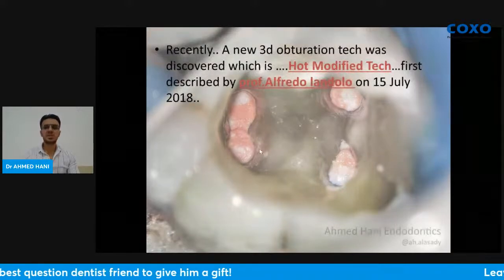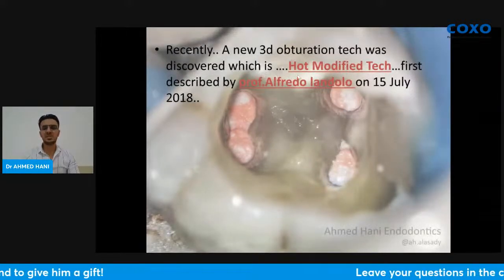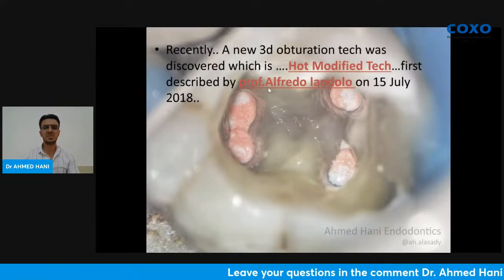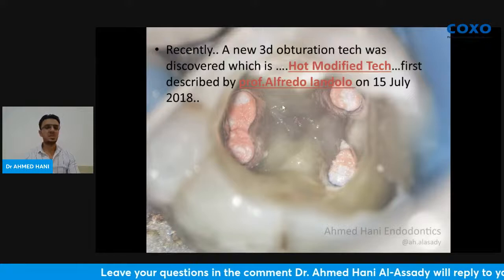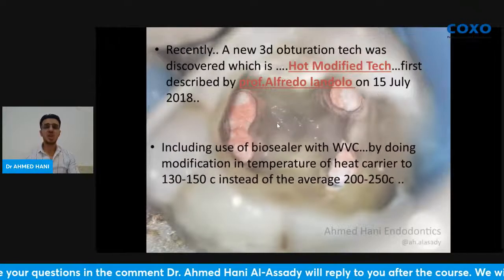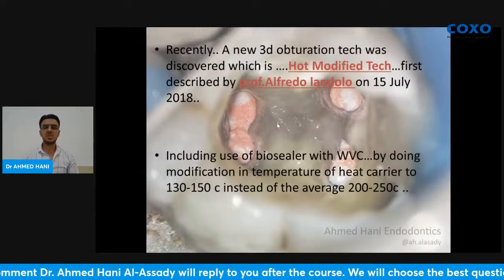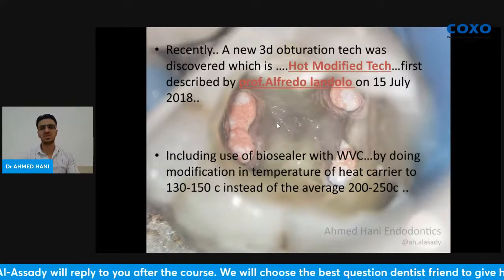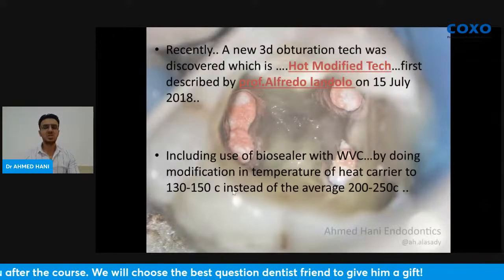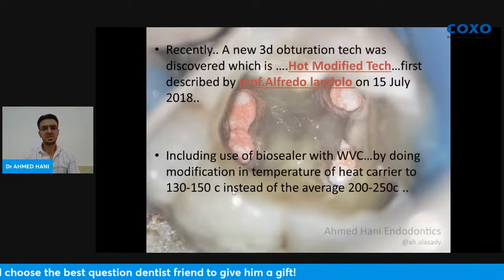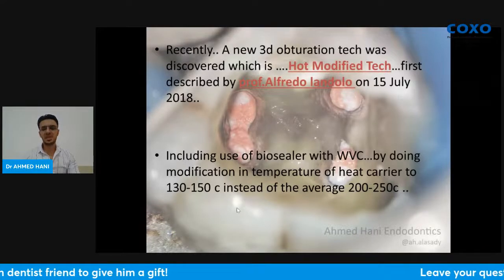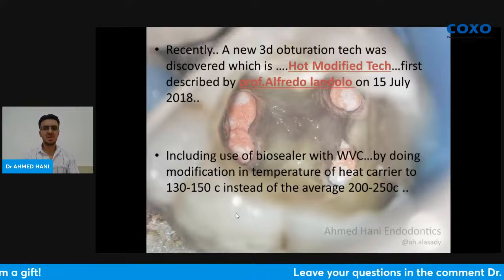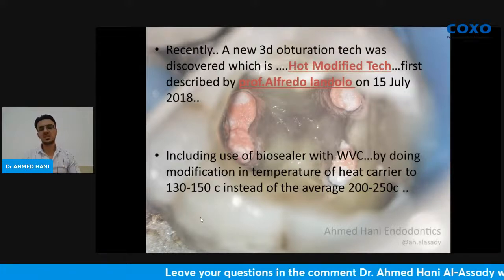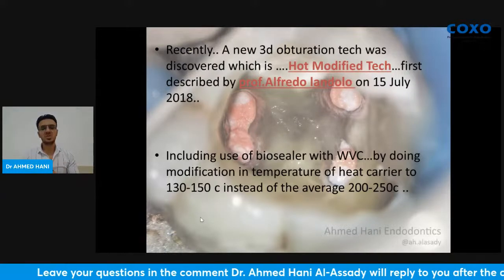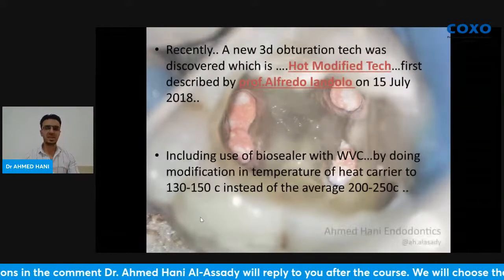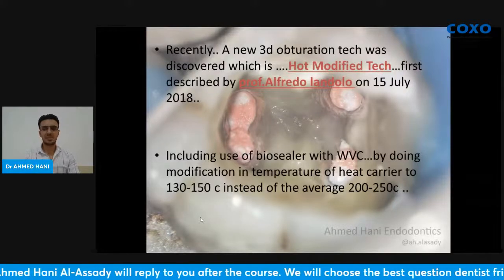Recently, a new 3D obturation technique was described, which is a hot modified technique first described by Prof. Alfredo Iannolo on 15 July 2018, including use of bioceramic sealers with warm vertical compaction by modifying the temperature of the heat carrier, the pen, to 130 to 150 Celsius instead of the average 200 to 250 Celsius. This minimizes the temperature in contact with the biosealer to control the material and prevent its setting rapidly.